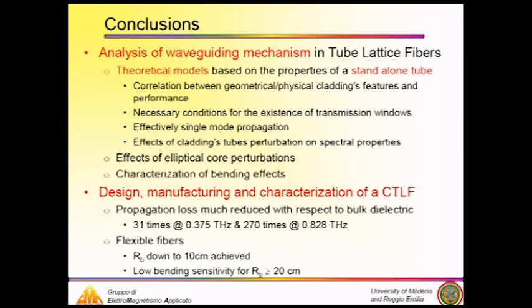So, in conclusion, we can say that during my PhD activity, I have analyzed the waveguiding mechanism in tube lattice fiber. And everything started with the consideration that the cladding can be studied starting from the single tube that constitutes its shape. And in particular, from this model, we were able to investigate the correlation between the geometrical features and the spectral performance, but also the conditions for the existence of transmission windows, effectively single mode propagation, and then finally, also the effect of the shape on the propagation loss.